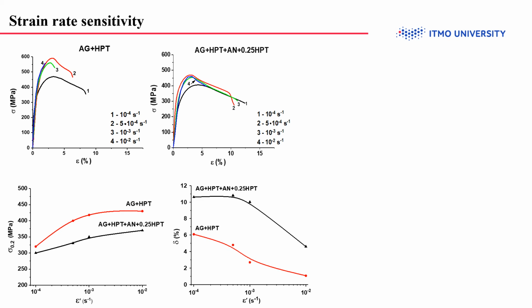With a further increase in the strain rate, the value of plasticity decreased to 5%. However, this value of plasticity is much higher than at a similar strain rate in the state after HPT, when the samples fractured almost brittle. This suggests that the relative effect of plasticization manifests itself in the entire range of strain rates under study.